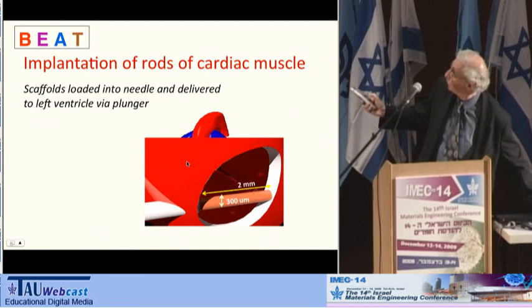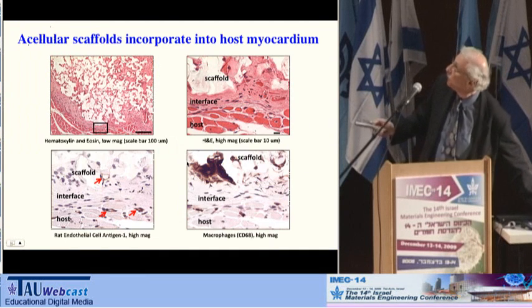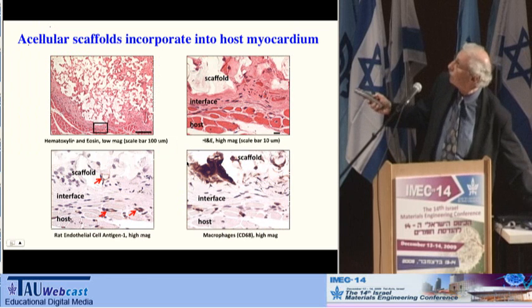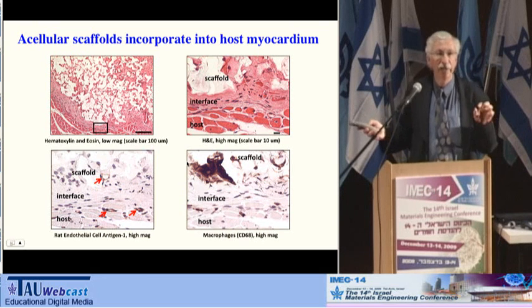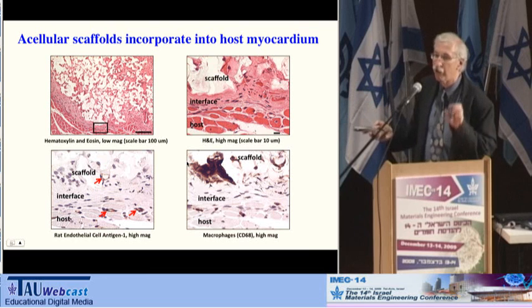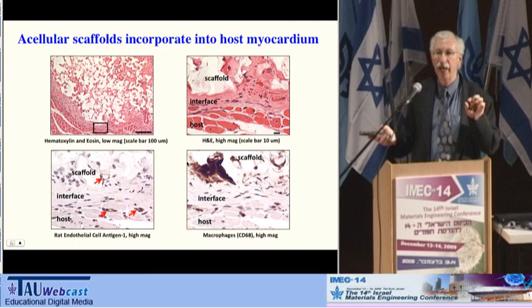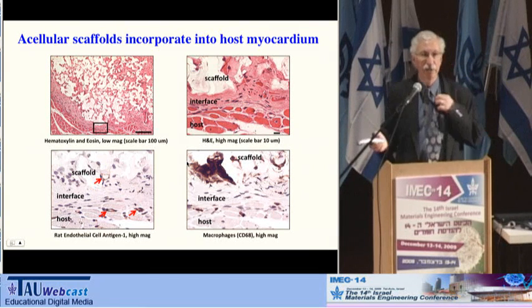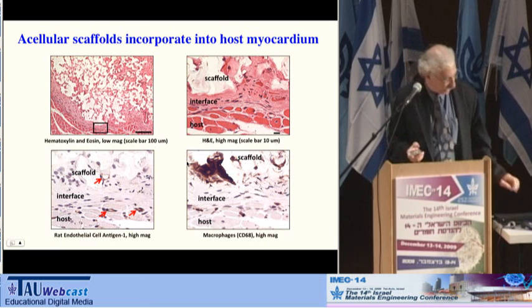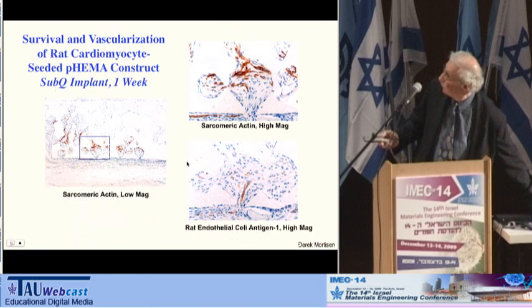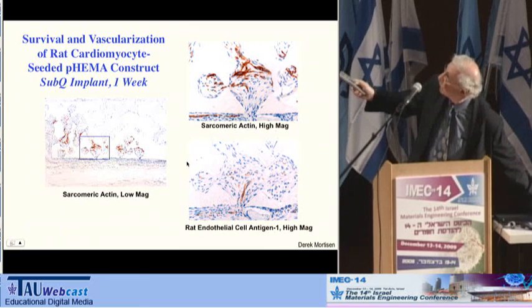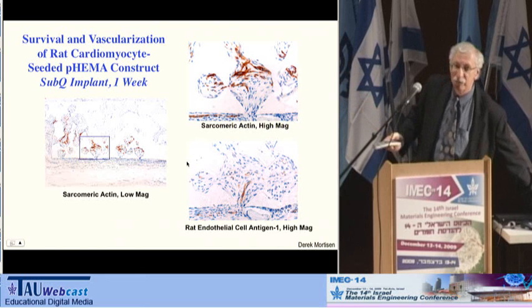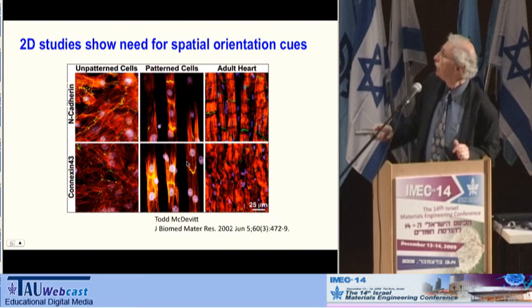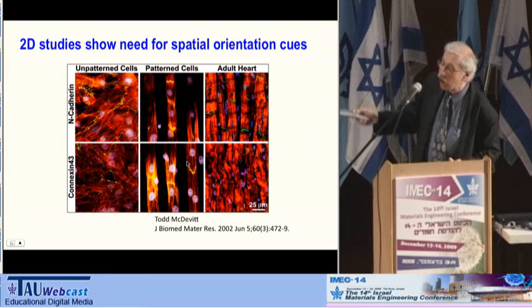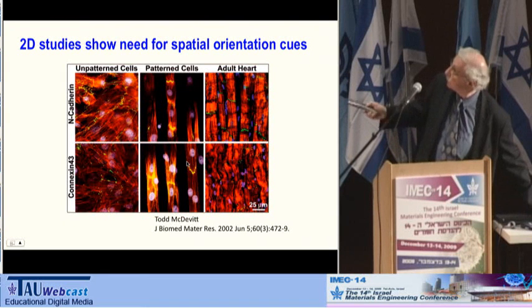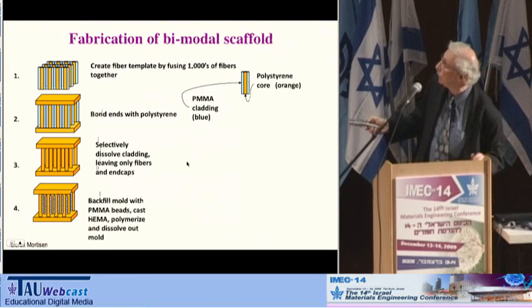Just shows an example of maybe the dimensions of these rods. They heal into this sphere templated scaffold heals beautifully into the heart. I'm not going to go into the detail for lack of time, but it heals very nicely into the heart, which is very subject to scarring, so that's quite interesting. And we can put these cardiomyocyte cells into the sphere templated material. They stay alive. We are trying to align the cells because the cardiac cells have to be aligned.